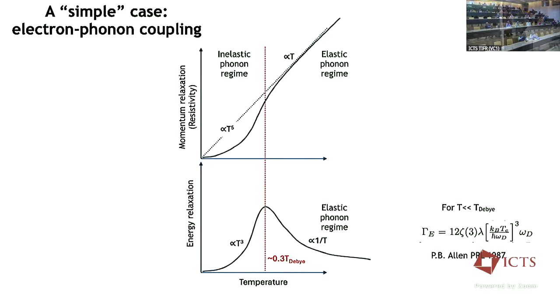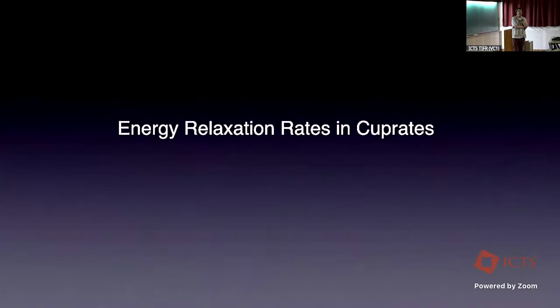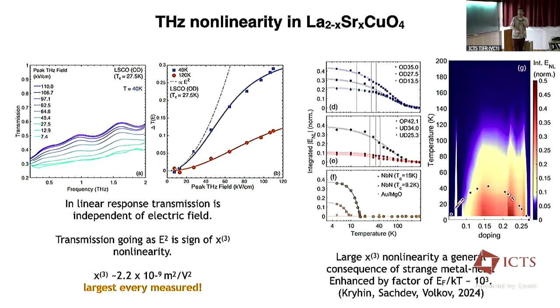Yeah, so it doesn't appear to. We don't have many films out there. Oh, where is it? There. Yeah. But that's the highest doping that we went to there, where TC was 0. Ivan doesn't really have a good measure of what the doping is beyond where we can, based on conventional wisdom, go from TC to a doping, but at dopings where TC goes to 0, we don't know what the doping is anymore. But you can see if the resistivity recovers T squared.